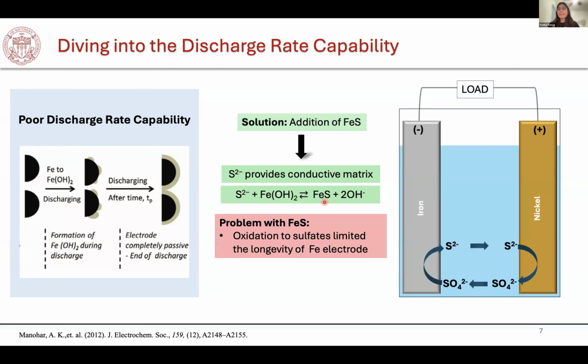With the passage of time, these sulfide ions dissolve and get oxidized at the positive electrode to sulfate ions. And the problem is converting sulfate back to sulfide. The reduction of sulfate to sulfide is kinetically challenging. This means that with the passage of time, the electrode is losing the depassivating reserve of additive. And this greatly worsens the life cycle of the electrode, where you have to add this additive every time so that you can go back to the better discharge capacities. So we wanted to find an alternate additive so that we can enhance the life cycle of the electrode, and we don't have to go back every time to add this exhaustible depassivating agent.